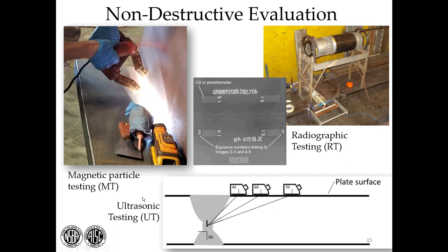Ultrasonic testing is another method. Here I just have a schematic. Here you see the plate surface, the weld metal, and transducers. The bridge welding code tells you that if you have a certain thickness of material, thinner material, you should use a 70-degree transducer and send sound to the weld. The technician who does the testing looks at an oscilloscope and observes the sound that bounces back from the other surfaces of the weld, and if a discontinuity is discovered, that will show up on the oscilloscope as a spike.